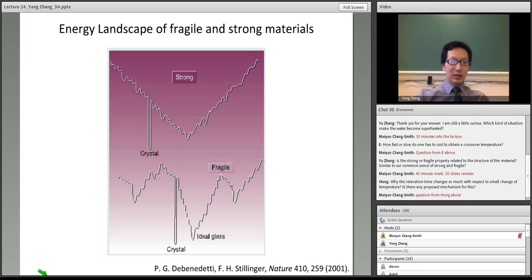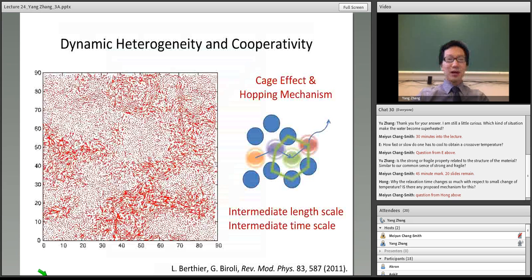Next I want to move to a very important concept, the so-called dynamic heterogeneity and cooperativity. This is probably the most popular opinion on the glass transition nowadays. The picture of the glass transition is that at high temperatures, every particle just needs to move by itself. But as temperature is lowered, for this green particle to move, the surrounding particles might need to open this cage. So in order for the relaxation to happen, several particles need to rearrange together for one particle to relax. This can give rise to the slow dynamics, which is called the cage effect or hopping mechanism.